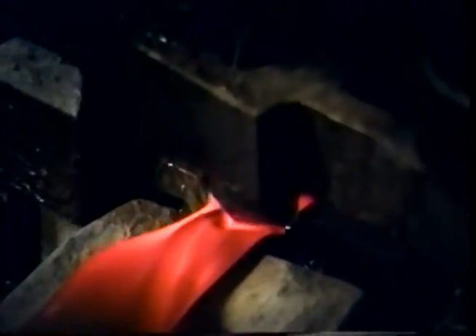He pushes the slug of beads down a chute at the back, where they go into a tall metal can for cooling. The dies are cooled with a water and soap mixture. This black glass bead simulates jet in Victorian jewelry.